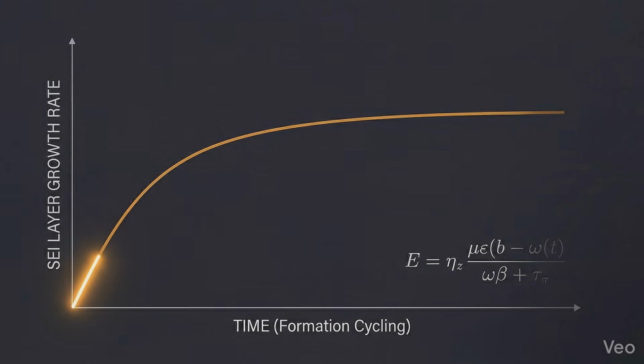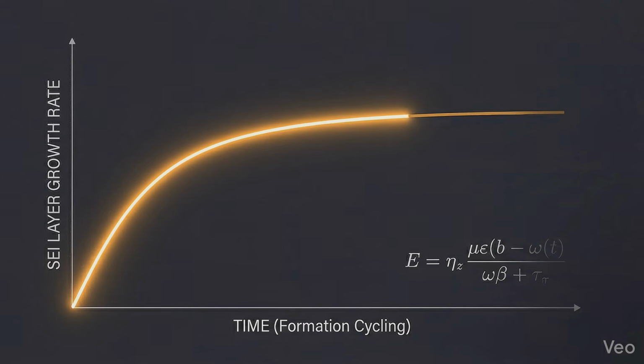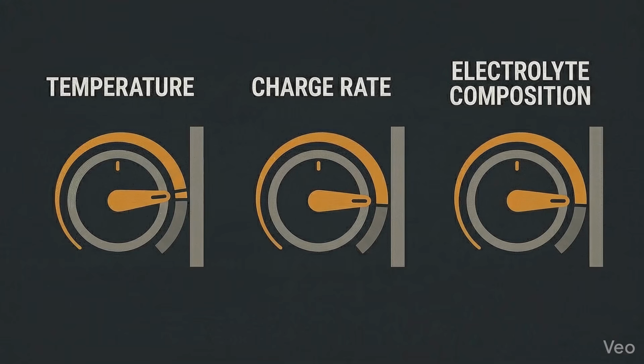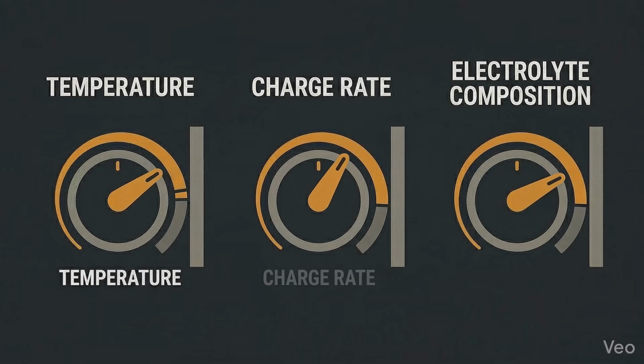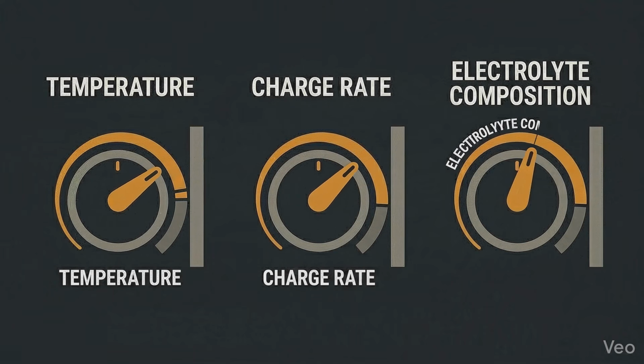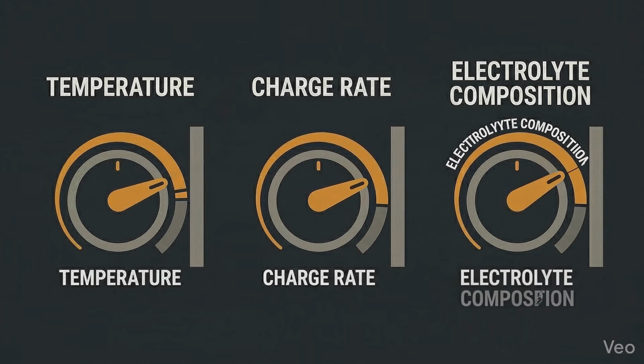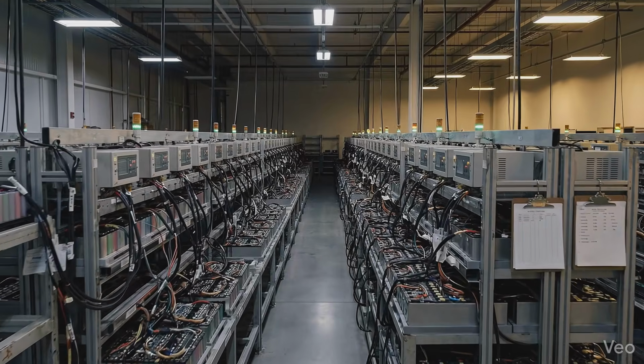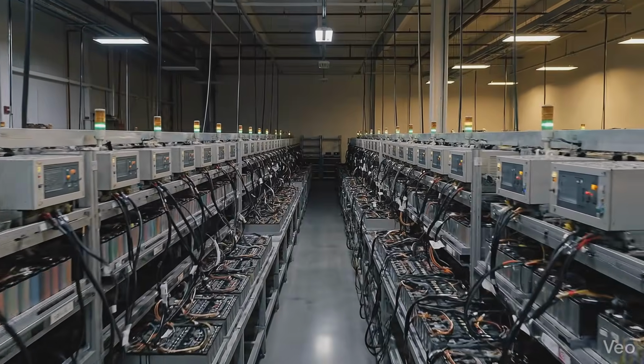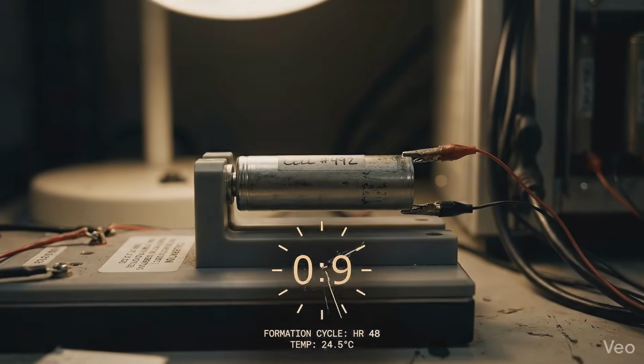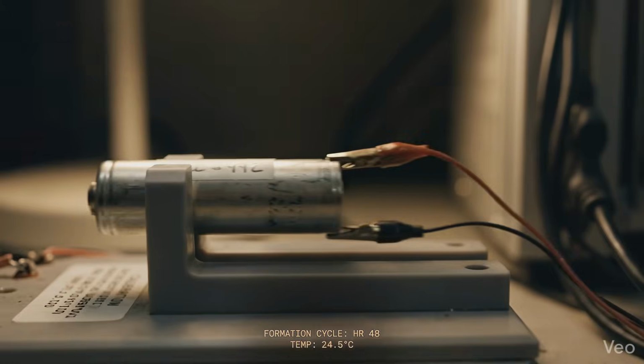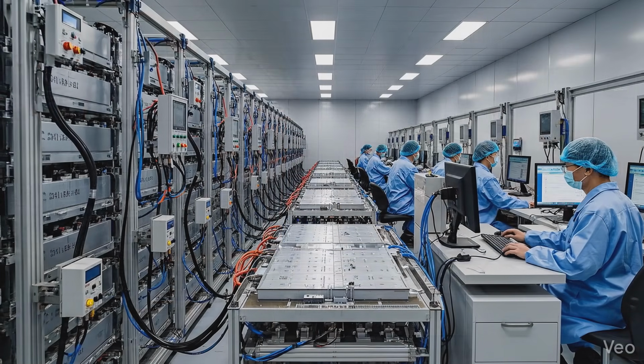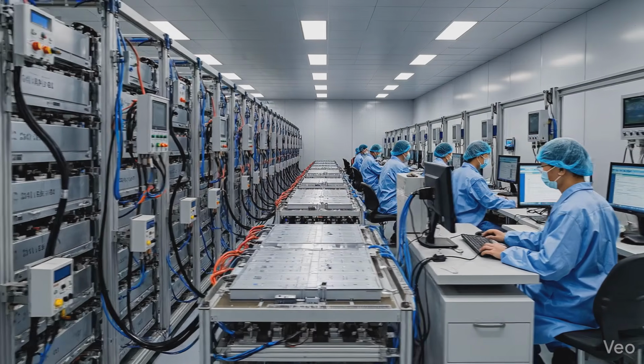The SEI layer forms at a rate determined by electrochemical kinetics. Formation conditions, temperature, charge rate, electrolyte composition can be optimized within limits, but there are fundamental physical boundaries to how much the process can be accelerated without compromising that protective layer. There is no robot that can substitute for the time the chemistry requires. The electrochemistry has its own schedule, and that schedule is written in physics, not in a production plan.